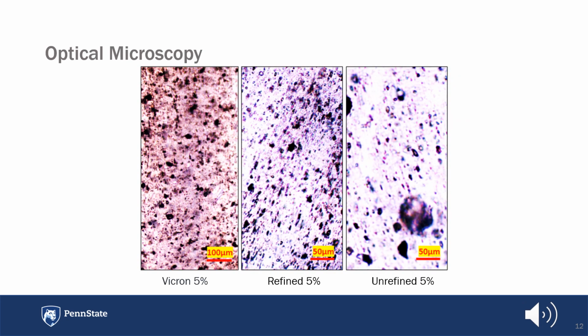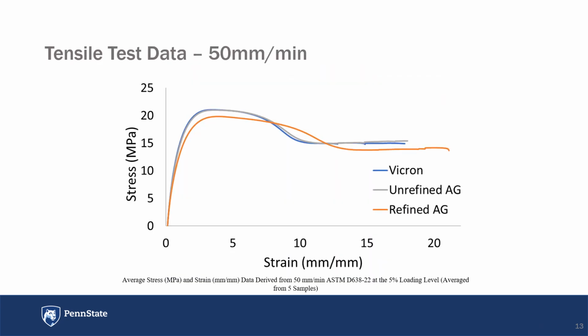We ran optical microscopy to ensure that our calcium carbonate was evenly dispersed throughout our polyethylene matrix. You can see in all 3 images below that we were able to achieve that. This slide presents an average stress and strain data derived from the 50 mm per minute tensile testing at the 5% loading level, averaged from 5 samples. The refined material exhibits a distinctive behavior compared to the unrefined and Vicron materials. This showcases different mechanical resilience under low strain rate conditions.